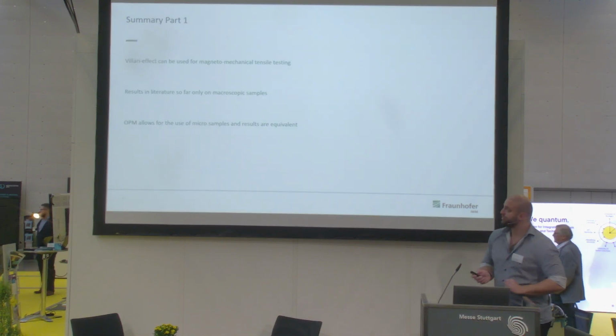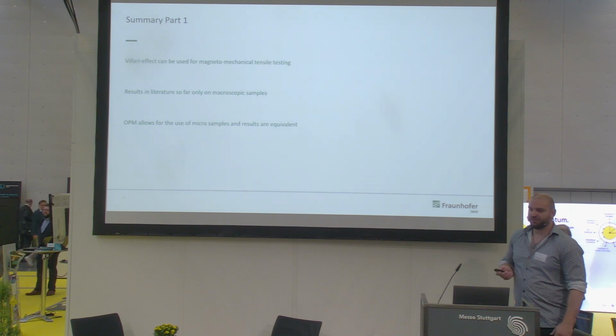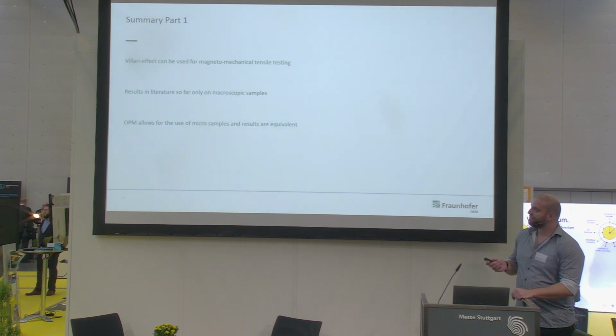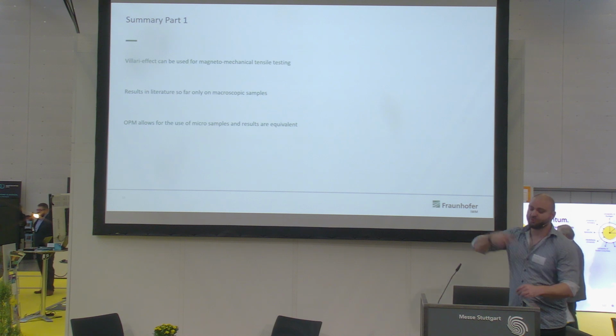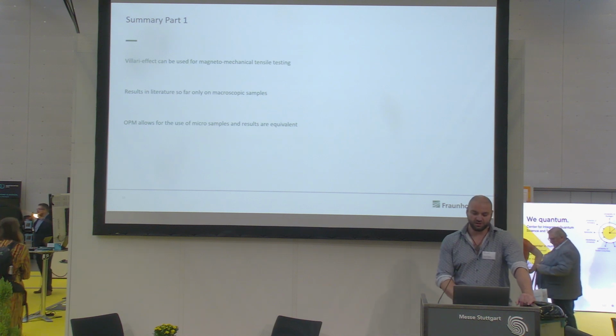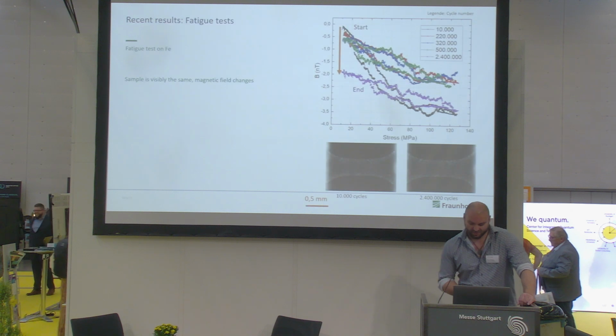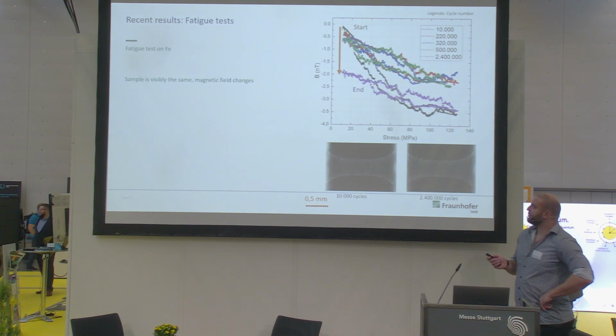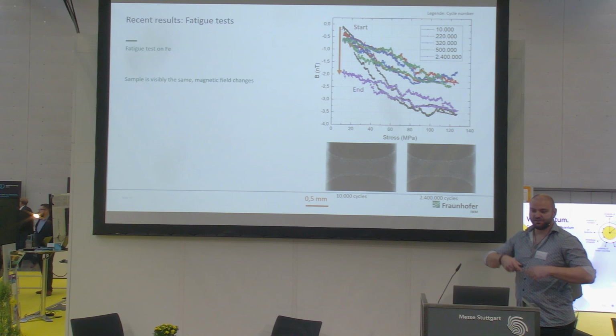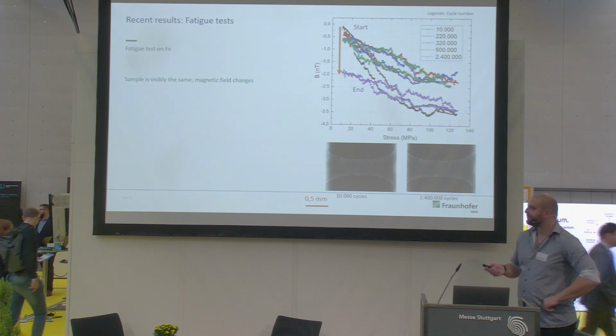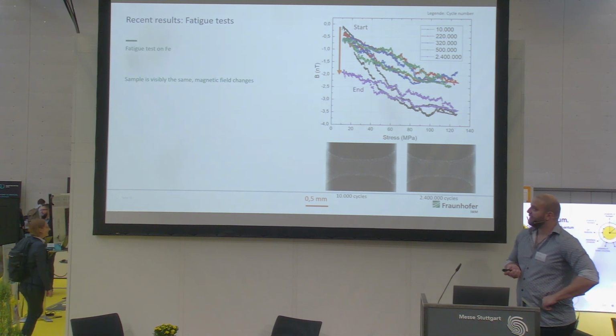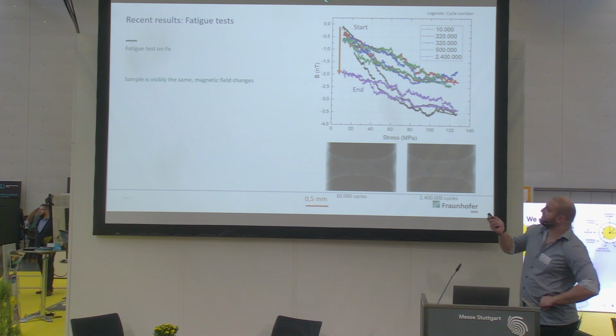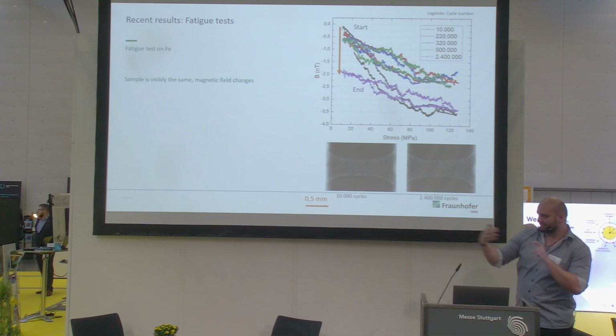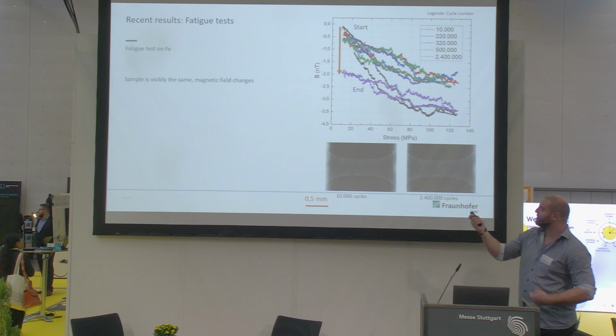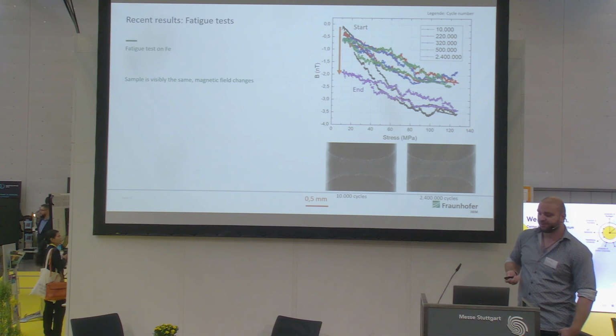To summarize part 1 for you, the Villari effect is used for magnetomechanical testing. The results in the literature are on huge samples, and we can reproduce this with OPM, with quantum sensing, on the small samples. So now what do we do with it? We've done a fatigue test, meaning we have a lot of loading cycles on a pure iron sample, which you can see down here. And a few things are happening here. On the top, you can see the magnetic field as a function of stress. And we do cyclic loading. We go back and forth with the stress. And every time we go back and forth, we generate one of these magnetic hysteresis loops here.